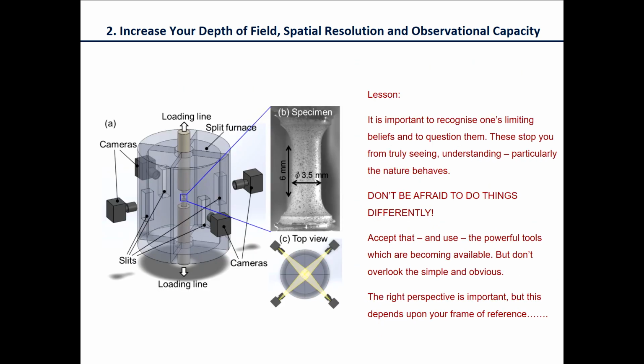Don't be afraid to try to do things differently. Here we had the idea of building a brand new furnace with windows that would allow us to have access to the specimen, but from many, many different sides. Because some of these materials are deforming anisotropically, which means that they tend to move out of plane. And we wanted to have a much better map of what the surface is doing.